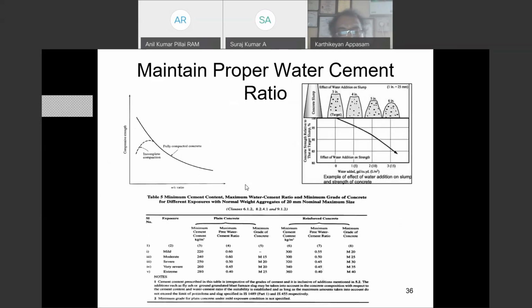Okay. And as we already discussed about the lack of proper water cement ratios, the slump cone is a matter of 2,000 rupees. Hardly 10% of my sites were using slump cones. When the cube strength is not achieved and we start scolding our contractors or site engineers, they say, sir, we did very nicely, sir, I show the video, sir. We don't want video. Have you checked the slump values? Most of the people don't know.